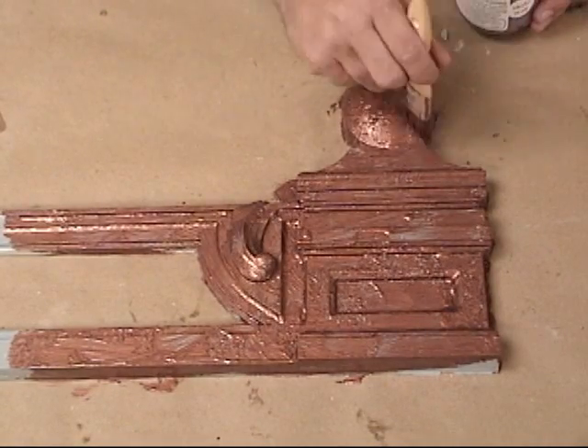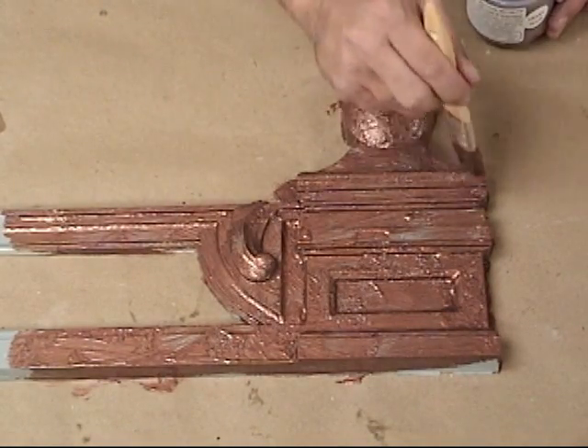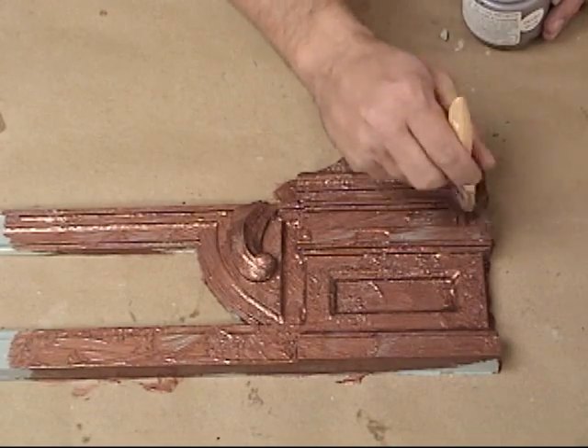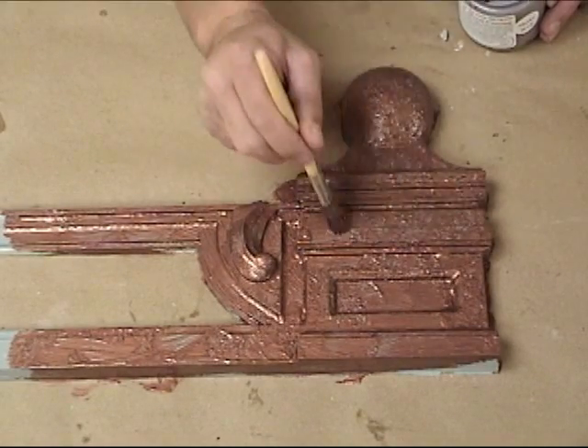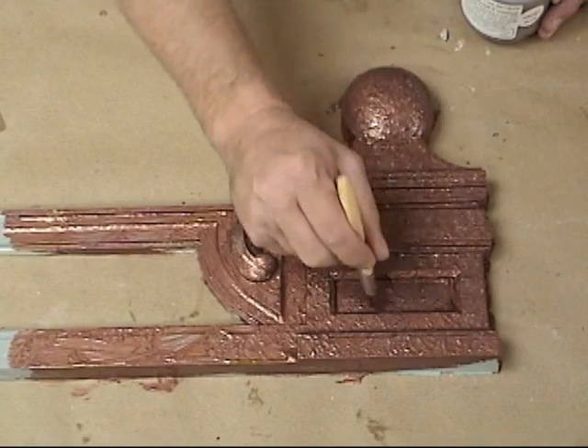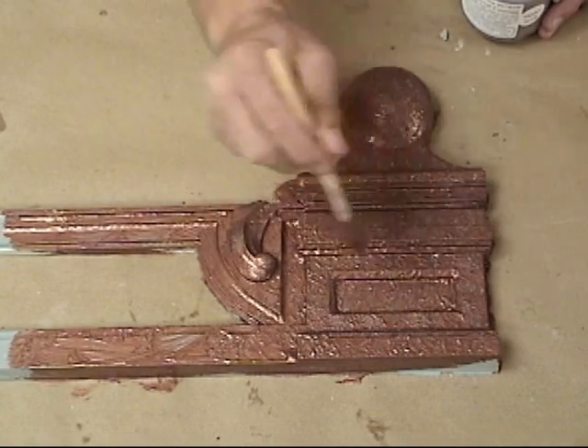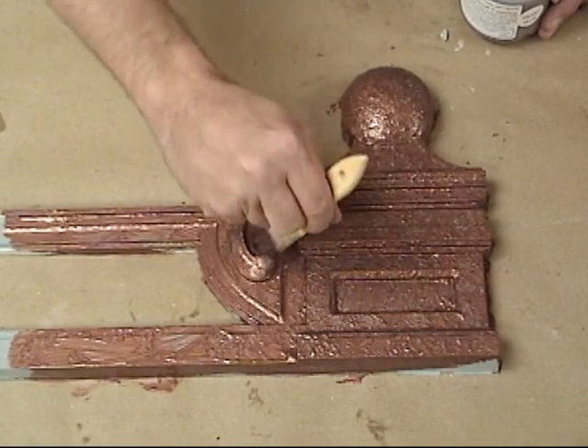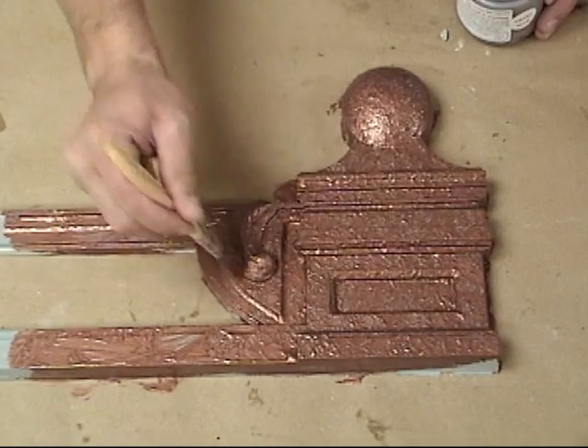And that accomplishes two things. When we start dabbing it like this, we get rid of the brush strokes, but it also gives us a nice texture that increases the surface area and gives our patina a lot of surface area to react with. And you'll see that in a minute when we spray on our light green patina.